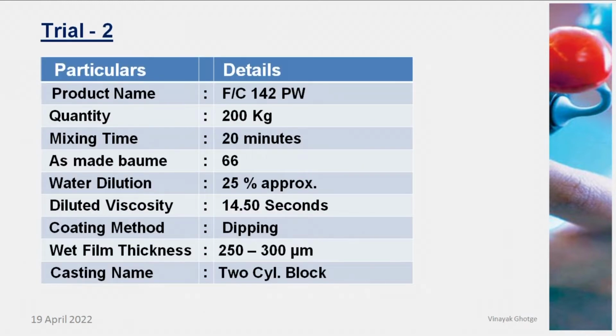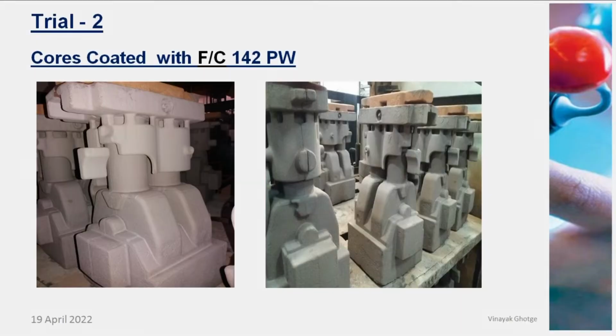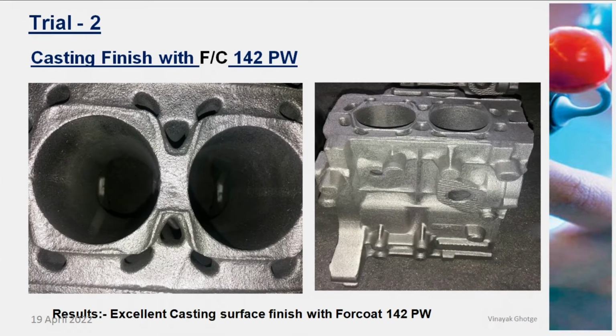The second trial which we have taken is again a critical casting. It's a water jacketed 2-cylinder block, and here also the coating is used by dipping process. Viscosity is around 14.5 seconds, and these are the cores which are dipped using the product, and this is the casting finish what we have got.